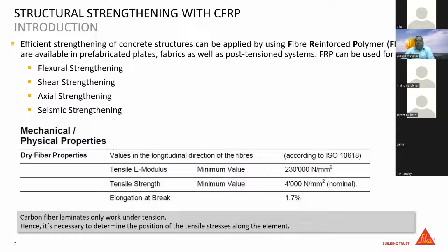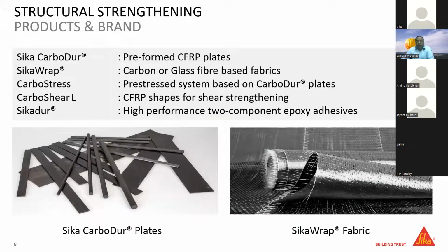So as an engineer, you can understand we are talking about a product which has much higher mechanical properties, especially the tensile property. Of course, the modulus of elasticity is also very high, like 230 GPa, which is similar to steel, and elongation at break is 1.7%. So this carbon fiber laminate or carbon fiber fabric can be used for strengthening of any RCC member, but it is very important that we identify the tension zone because the CFRP works only in case of tension. I'll explain in another slide.